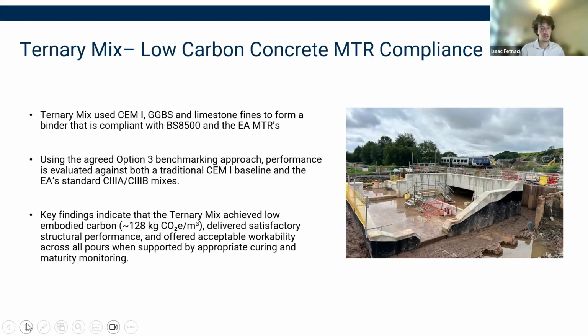So MTR compliance. The ternary mix incorporated CEM I, which is an OPC cement, GGBS and limestone fines to form a compliant ternary binder that meets the BS 8500 concrete standards and the latest update of the EA minimum technical requirements, V12. We used the agreed option 3 benchmarking approach, where performance was evaluated against both a traditional CEM I baseline and the EA standard CIIIA and CIIIB mixes.